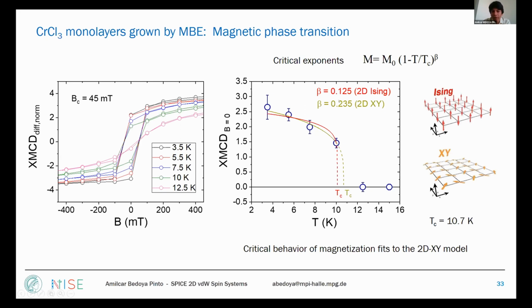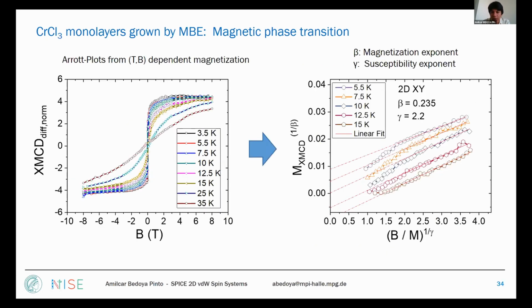temperature-dependent magnetization, our fittings agreed rather with a 2D XY model than with the Ising model. This is a remanence value that we took from the hysteresis loops, and the extracted TC that we got is 10.7 K if you consider a 2D XY model. And last but not least, we also did an Arrott analysis. For that, you don't rely on the low-field region of the magnetization, but on the high-field region of the MH curves. And with some scaling laws, you are able to get the critical exponents for magnetization and susceptibility.